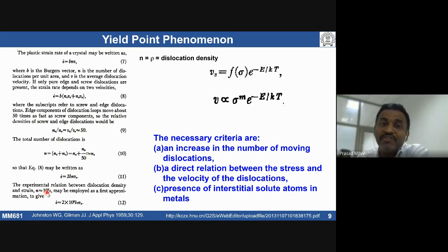Because of this rapid increase in dislocation velocity initially, that can lead to instability in the deformation. Though I'm applying a particular strain rate, locally I see very high strain rate in the material, and that can lead to instability in the deformation. As a result, we see a drop in the yield stress of the material.